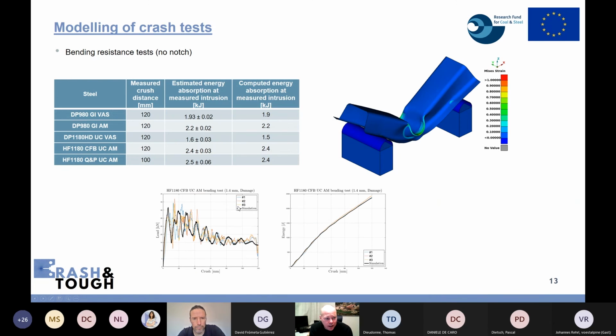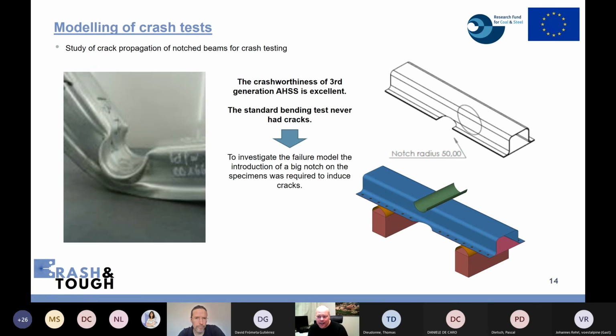On the other hand, if we have bending resistance tests without any notch, we are more or less spot on if you compare the measured with the computed. But on the other hand, we don't have any failure here, so you can't say anything. You can't validate the failure mode criteria that have been used. What you can say is that maybe the flow stress model that we have obtained is good enough. But once again, we need some kind of failure. So therefore, I will let Ricardo conclude this presentation.